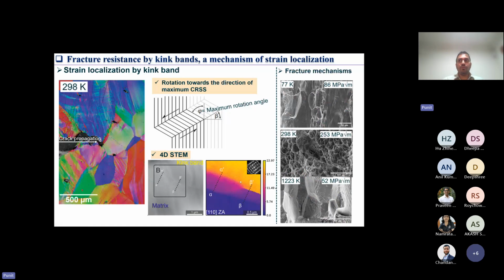And because of this formation of kink bands, if you look at the fracture surface, the fracture mechanism changes from cleavage to microvoid coalescence to intergranular fracture at high temperature. In all these cases, because the kink band is driving damage away from the crack tip, you are getting higher fracture resistance. So that was really interesting to see.